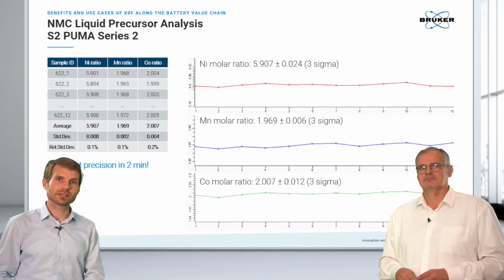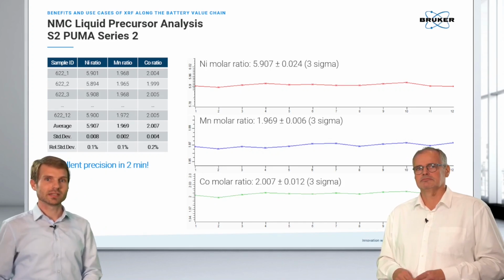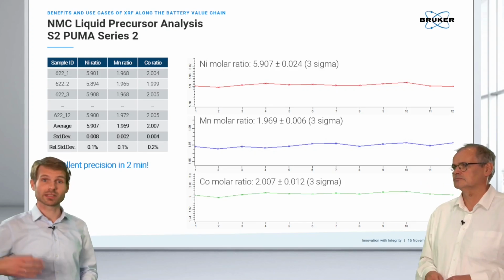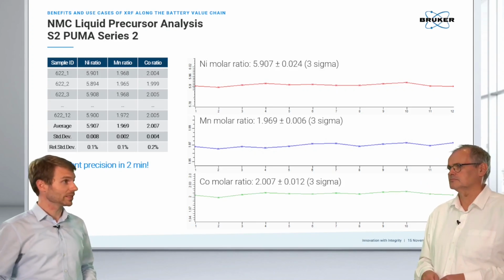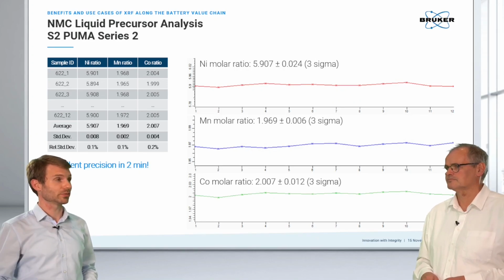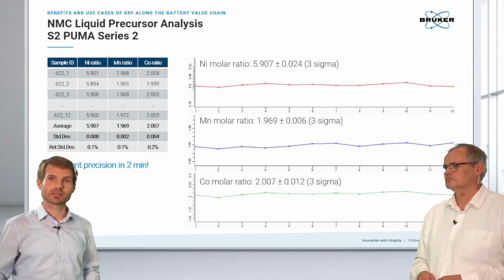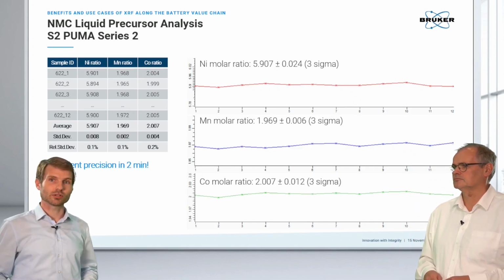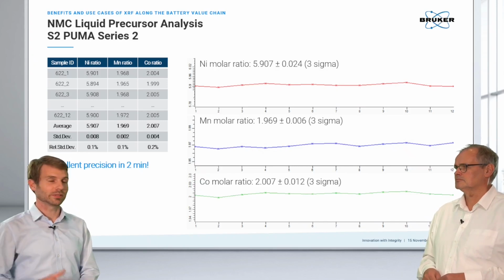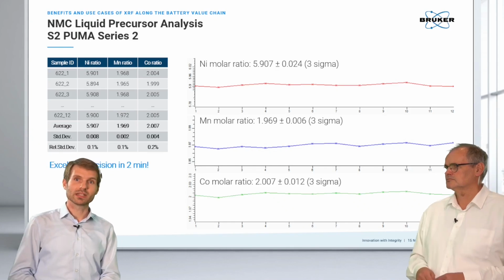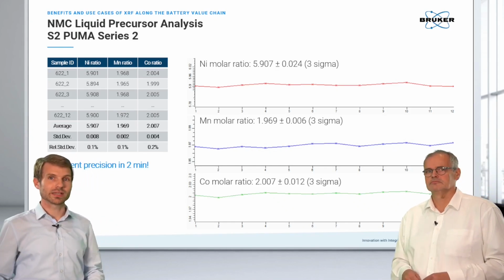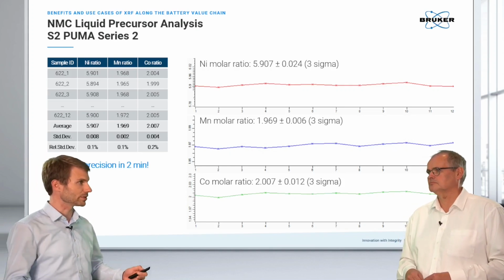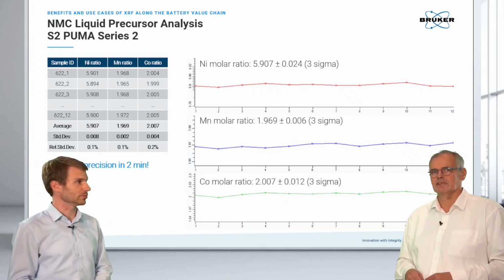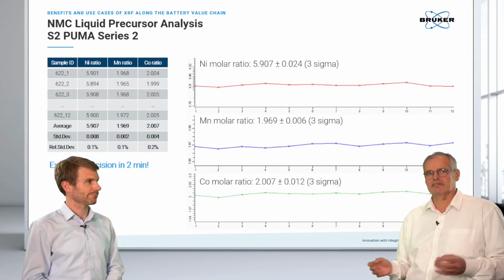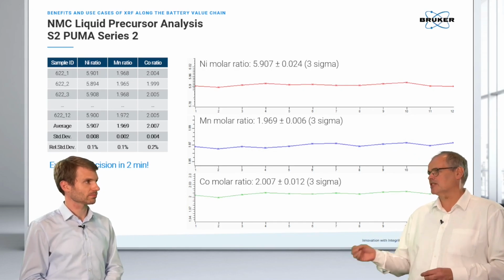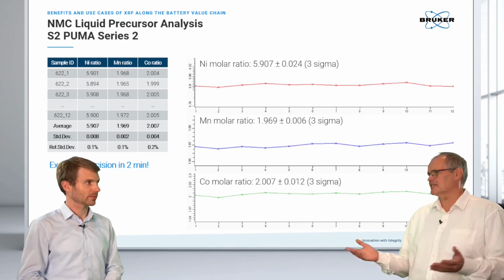And last but not least, for this liquid precursor use case, just a precision test here. We remeasured the sample 12 times. We prepared it each time, we loaded it each time, so really as in the real world, not measuring the same sample every time. And you can really see that we have an extraordinary stability here. We produce a relative standard deviation of around 0.1% for nickel, manganese, and cobalt. And we can then easily determine what our thresholds are and meet them, in just 2 minutes. So the relative standard deviation is excellent here and enables very close monitoring of the production process. That's it.